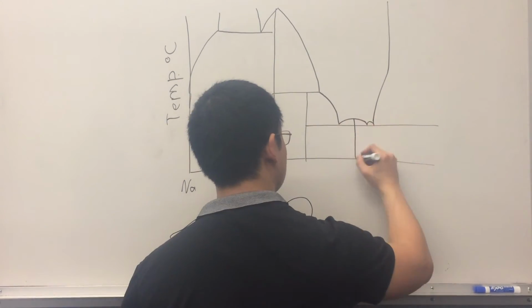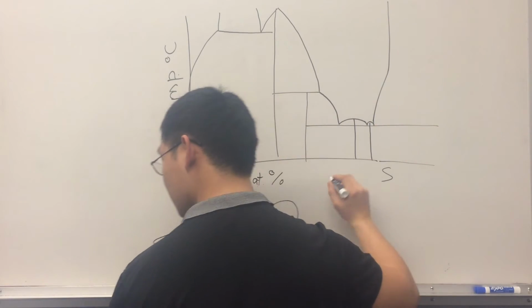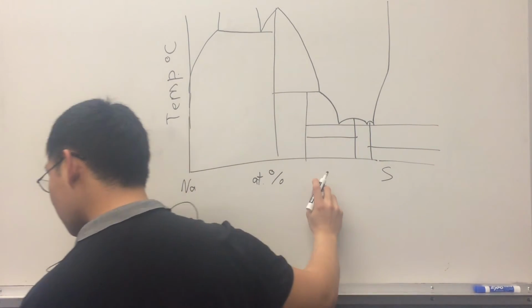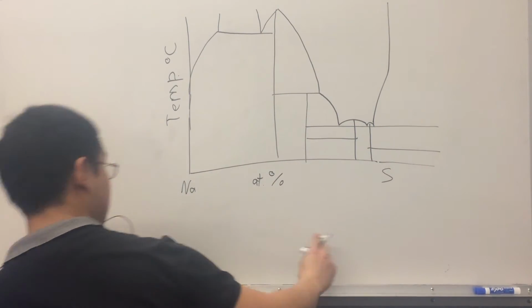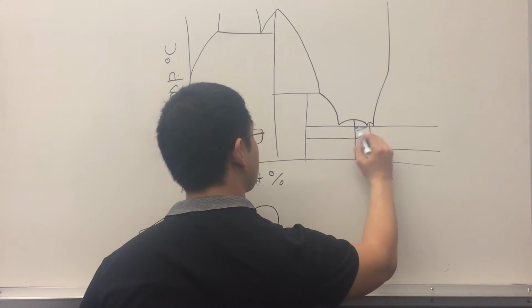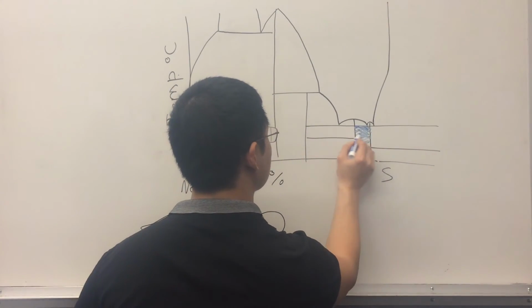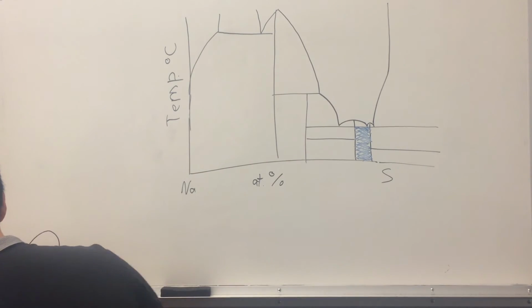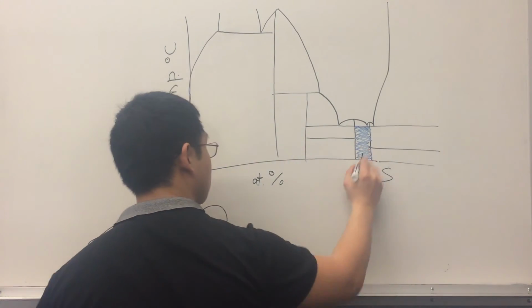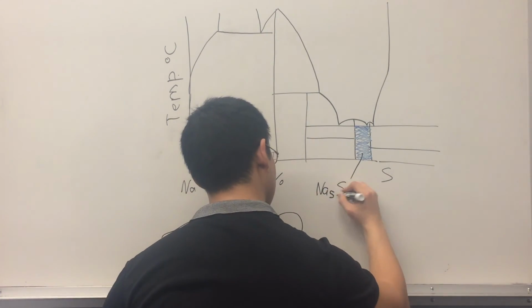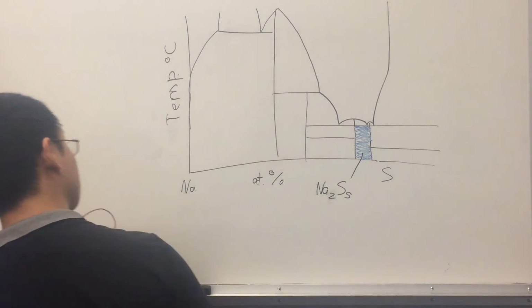In the application of disodium pentasulfide for molten salt batteries, the removal of liquid sulfur from the electrode surface in the two-phase region is important in order to achieve high specific energies. The solution of the problem requires ways to improve the mass transport properties within the graphite matrix. This can be achieved either by increasing the mass transport rate of sodium sulfides to the solid electrolyte and/or the rate of sulfur removal from the electrode surface. The disodium pentasulfide phase is highlighted on our diagram.